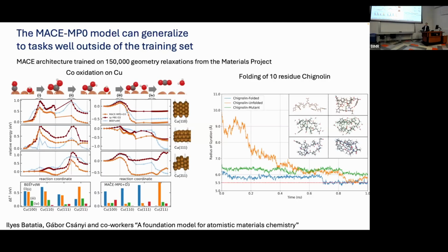There's been a lot of work on how DFT can be accurate, or also where it can fail. One case where it really does poorly is mapping out dimers, because there are no dimers in Materials Project. So like chromium dimer, it's not going to do very well. So this is not to say that the MACE MP0 model can replace DFT out of the box, but it's to say that in terms of trying to obtain a generalizable, transferable model, this is an interesting demonstration.